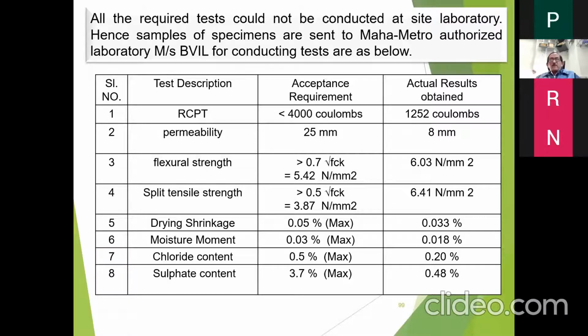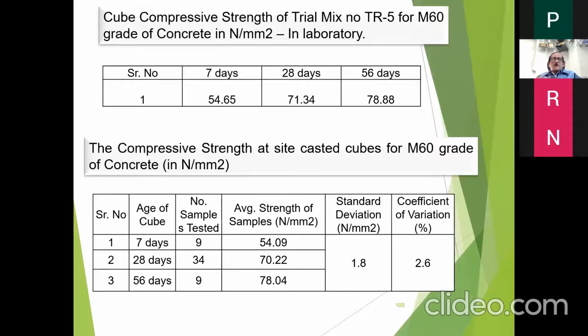And permeability of 8 mm against the required 25 mm. Flexural strength also was good, more than required. Split tensile and drying shrinkage were also very low. Moisture movement, chloride content 0.2% against 0.5%, and sulfate content. So all the values were very good, and in general the cube compressive strength we also evaluated for 7 days,